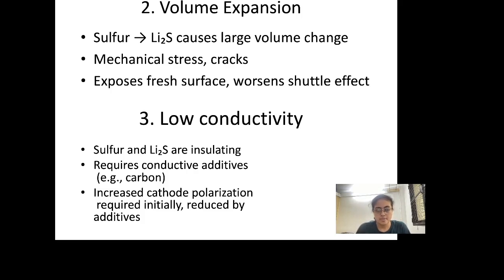So the third point is that essentially electrode sulfur, elemental sulfur, and as I mentioned before, lithium sulfide, are low conductivity compounds and elements. Their conductivity is very low. In fact, I have written down, it's as low as elemental sulfur being 5 x 10^-30 Siemens per centimeter, and lithium sulfide being 9.21 x 10^-9 Siemens per centimeter, right?